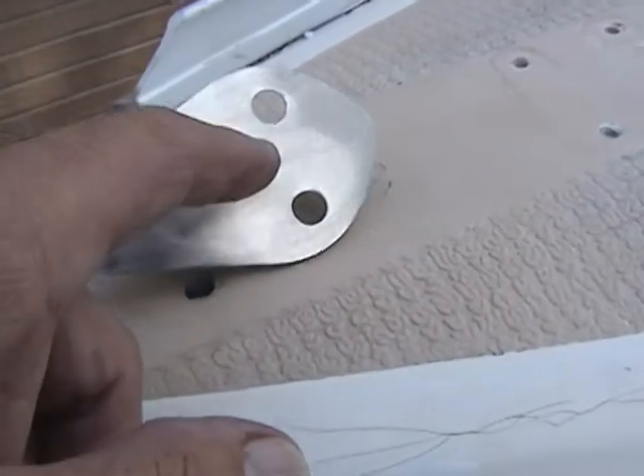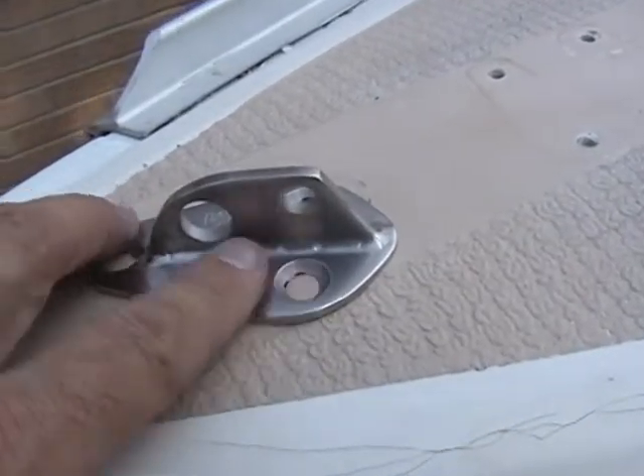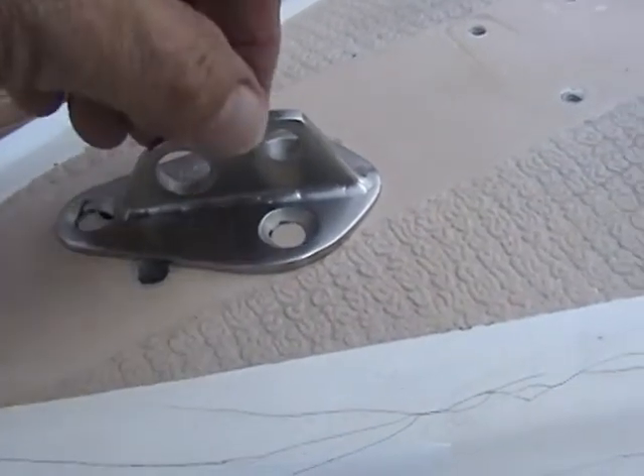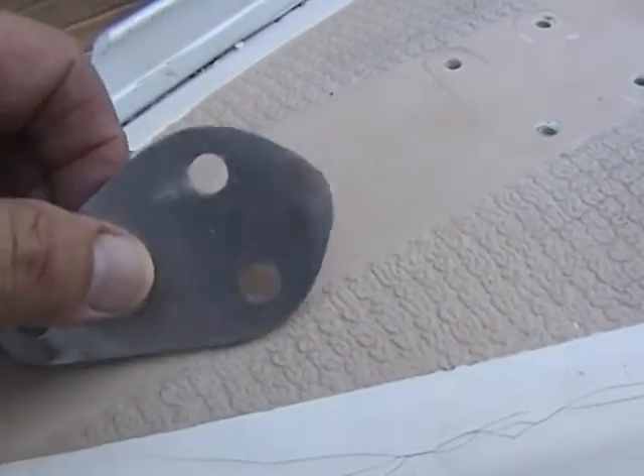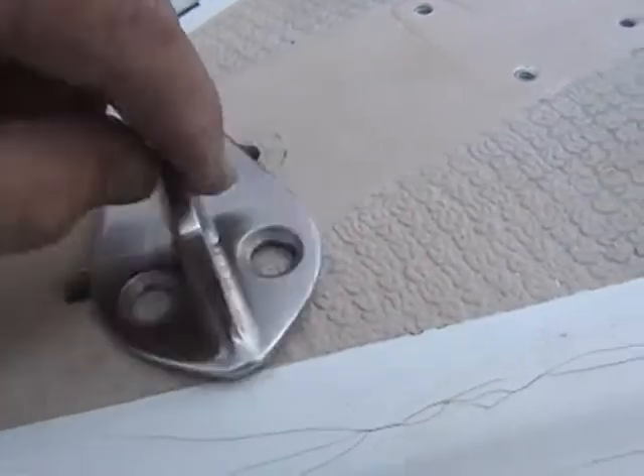And there was a crack. How this was made was a piece of steel — they cut a slot in the flat bottom piece, inserted the upright piece, and they only welded it on the bottom. On the top, there was no weld at all on either side.